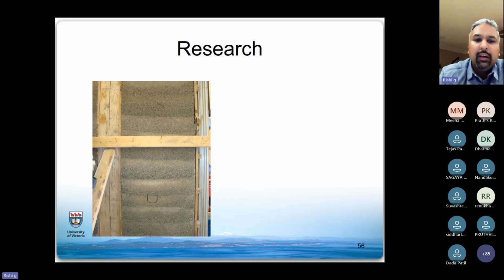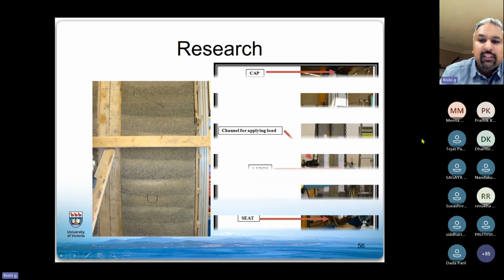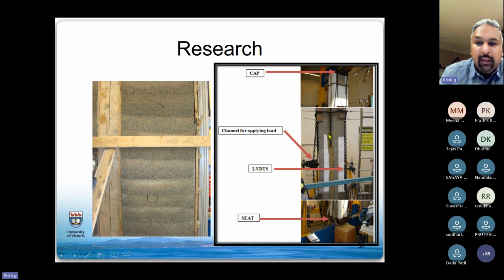So there are a lot of people trying to use rammed earth to blend with nature, right? If you use local soil and construct your structures, of course, you're going to blend well with your native environment because it is native material, and it does have a little bit of a natural sedimentary rock look. This is showing you full-scale wall testing. If you can't figure this out, this is insulation in the middle, with 2 rammed earth sections on the 2 sides. That's the sandwich wall cross section. We just painted it white because we wanted to see where cracking was taking place. And here's a load cell, and we are applying a lateral load. We were trying to find out the out-of-plane bending strength.